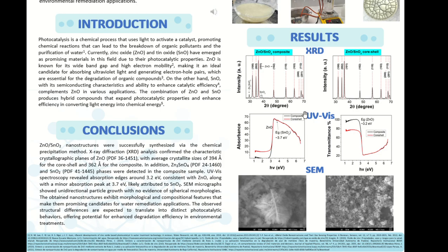UV-vis spectroscopy revealed absorption edges around 3.2 electron volts, consistent with zinc oxide, along with a minor absorption peak at 3.7 electron volts, likely attributed to tin oxide. SEM micrographs showed unidirectional particle growth with no evidence of spherical morphologies. The obtained nanostructures exhibit morphological and compositional features that make them promising candidates for water remediation applications. The observed structural differences are expected to translate into distinct photocatalytic behaviors, offering potential for enhanced degradation efficiency in environmental treatments.